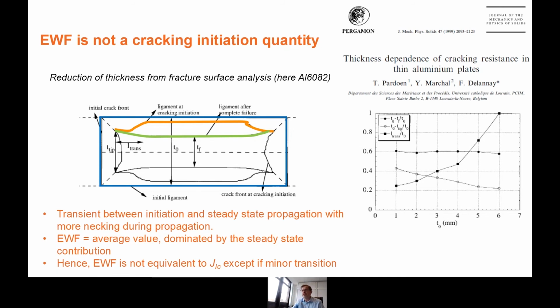The thickness reduction at cracking initiation is smaller than during propagation, which means that during propagation, the necking expands more, which means more energy for necking. And so the essential work of fracture, being a combination of a fracture work and a necking work, the necking work keeps evolving and growing during propagation. And that's certainly most of the time the main reason for which the initiation essential work of fracture is not equal to the propagation value.